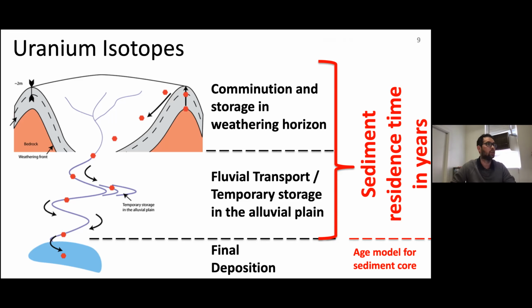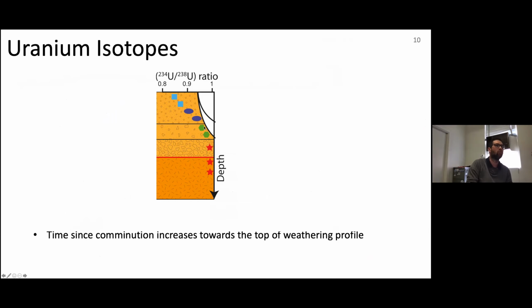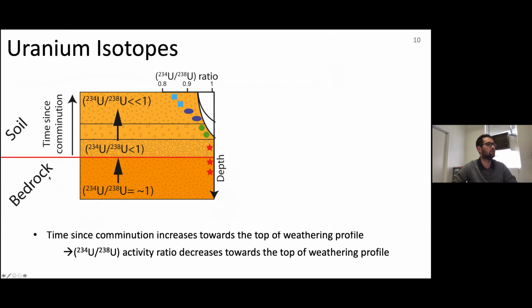If we then zoom in one step further and really try to understand what happens in our weathering profile, if we have our bedrock here, the interface between the weathering horizon of soil and the bedrock. I said previously that bedrock closed system will have activity ratios somehow close to 1. We produce our fine powder here at the interface. So this is why this material close to the interface will still have activity ratios closer to 1. And since the interface between the soil or the weathering horizon and the bedrock moves downwards over time, material in the upper part of the soil profile will be stored for extended time. So this is where we increasingly lose our daughter nuclide uranium-234, and we find this trend towards decreasing activity ratios towards topsoil layers. And that's also what Tony has been working on for quite some time, to show that in various weathering and soil profiles across Australia in particular.